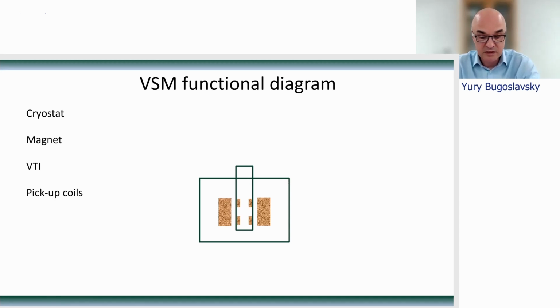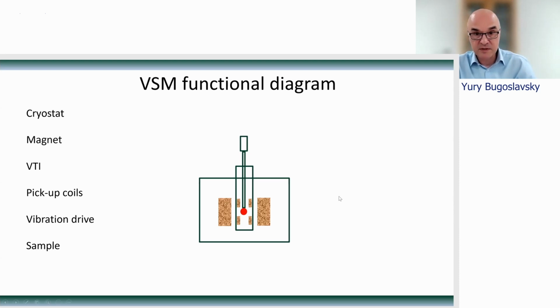For the VSM, we need an actuator or drive, which will produce regular mechanical vibration. The drive sits at room temperature on top of the system. The sample is connected to the vibrator via a long, rigid rod, and the sample is placed in the center of the magnetic field.